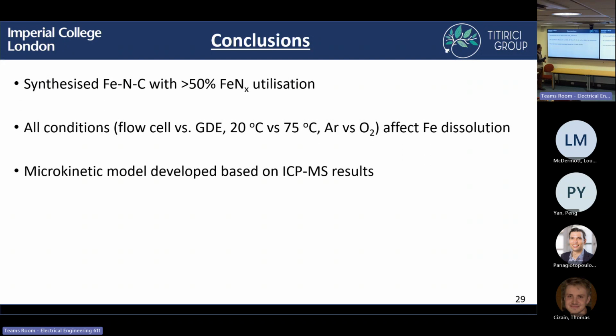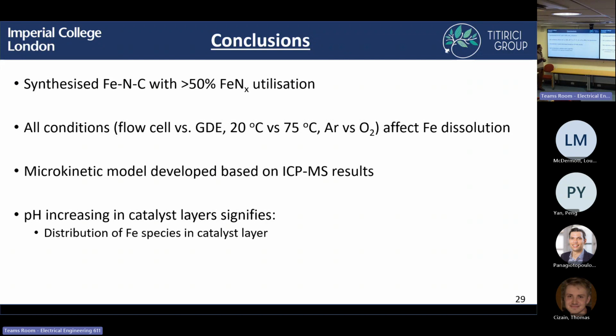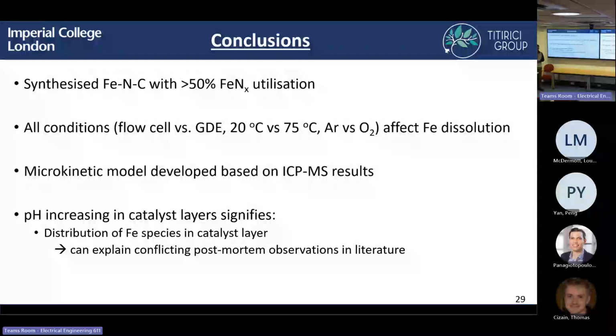So we're able to, well, I didn't, but Antoine developed a microkinetic model based on the results. And we saw that there was a significant increase in the pH. And there's some important implications for that. One is that there's a distribution of different iron species in your catalyst layer. So depending if you characterize the interface or characterize the backside of the catalyst layer, you'll see different things. And so this explains, I think, partly why there's some conflicting post-mortem observations in literature, because it really depends where you're characterizing the catalyst.